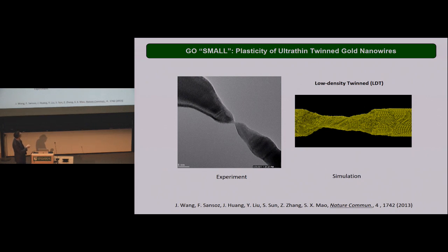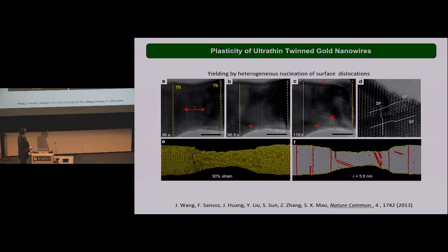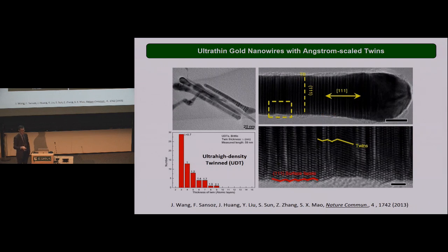So that shows clearly some large plasticity. And again, this is well established. This plasticity results from the nucleation of surface dislocation. So there's nothing new. Now what we did is we look at another type of wire, but these are made by solution process synthesis, and they do form a very high density of twins. So we call this the ultra high density twin, and it's quite amazing.